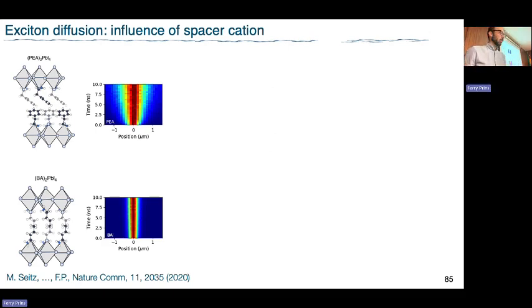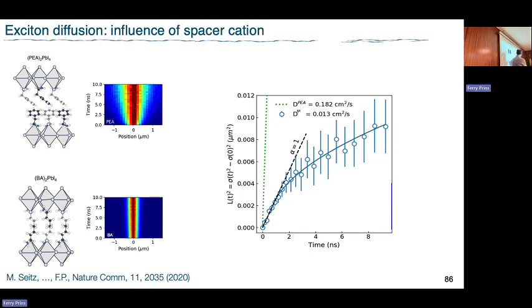But because we have a super resolution technique, you can still analyze this and still get the same behavior, just at a very different order of magnitude. You still see that it broadens linearly still in the beginning and it slows down again. But you get an order of magnitude difference in diffusivity just by changing the organic cation that is separating these inorganic layers, which is where your excitons live. So the organic things should not actually affect very much your excitons, but they do for some reason.